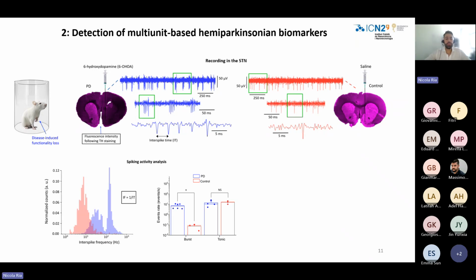This difference can be quantified over time by looking at the interspike frequency, so 1 over the interspike time, the time between two consecutive spikes. And in the case of the Parkinsonian animals, there are two peaks. One sharp peak at high frequency associated with the bursts, so with the biomarker, and then a broader tonic peak, at lower frequency, associated with this second component of tonic spikes. While in the case of the healthy animal, there is only one peak at a low frequency.